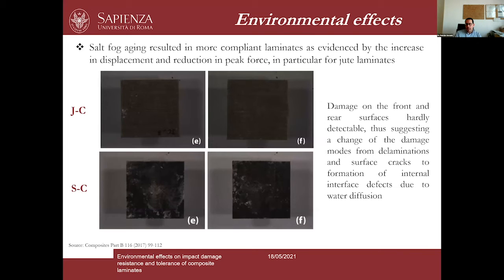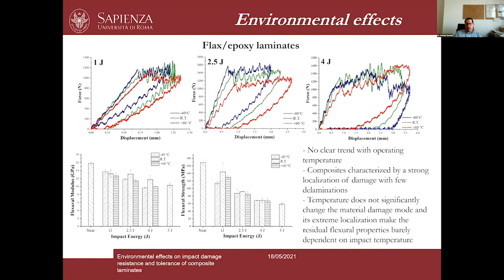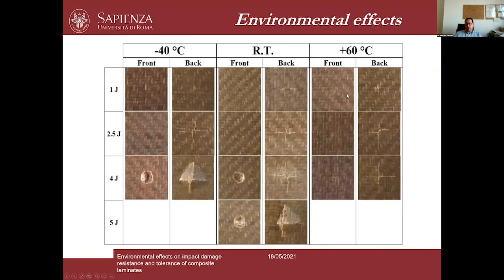So this is something really interesting with these natural fiber composites. These are instead some pretty new results on these flax epoxy composites. These composites were tested at different impact energy levels, and this time we tried to address the effect of temperature. During the impact, we changed the temperature, so these impacts were performed at room temperature, at -40 degrees Celsius, and at +60 degrees Celsius. Again, if we look at the force versus displacement curves, it is pretty clear that there is an effect of the temperature. And there is also an effect, for example, on the damage modes.